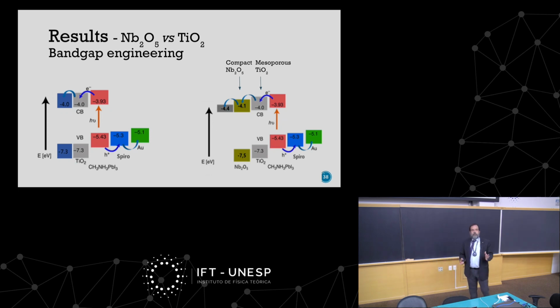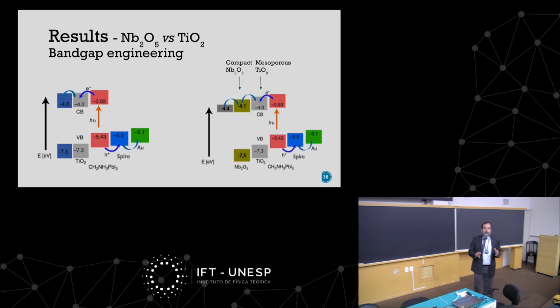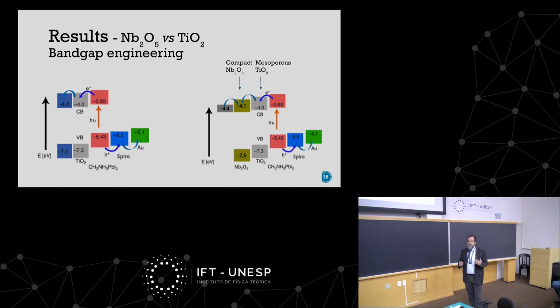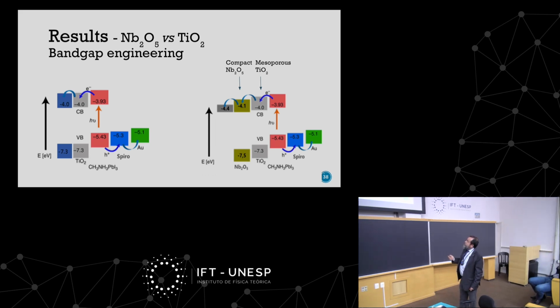So why? That's the question. And our answer is that what we did is basically what is called band gap engineering, which is well known for the semiconductor community. So by putting another material very close to TiO2, but TiO2 is the one which is extracting first the electrons, okay? The mesoporous part, these nanoparticles are close to the perovskite. So the perovskite, when the electron makes its first transfer out of the perovskite, it goes to TiO2. And then it has the niobium oxide layer and then the metal, the semi-transparent metal. So the electron transferred to here, and then it's transferred to here, and then to here. So it's like a little ladder.